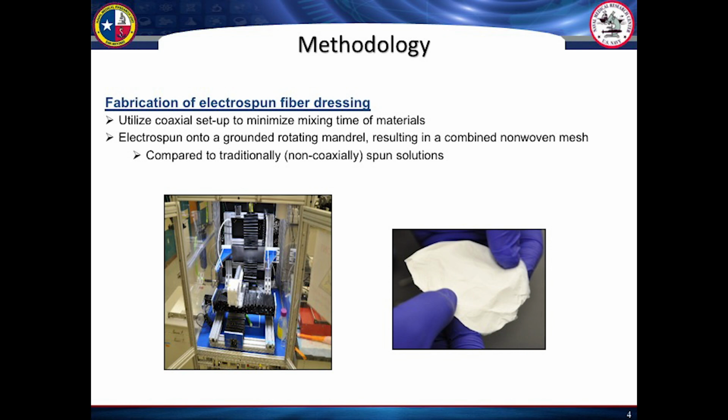So electrospinning, basically, you're going to make a cotton-like scaffold. So just like your shirt or anything like that, that's kind of what it's really gonna feel like. And these are actually a little special because they're on the nanoscale. So all the fibers you make are extremely, extremely small. And because they're small, that means you have a lot of surface area, you have a lot of porosity, that means that it's breathable, and that means that you can actually have a lot of contact to the wound area, meaning your released drugs can release faster than some of the other methods, such as spun bonding per se.